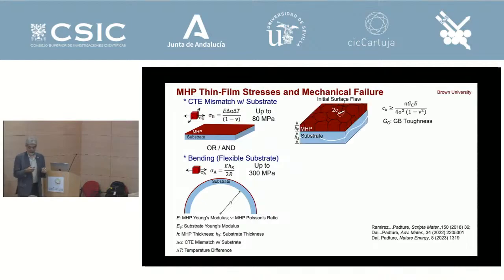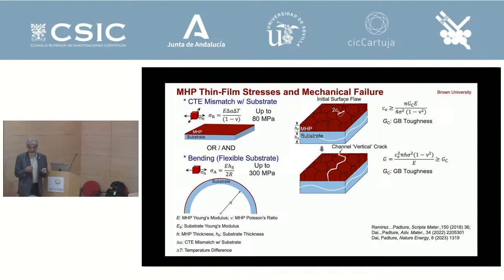But you have these residual stresses, which can be amplified if it's bending. And then you can have cracks, there are always cracks, and these stresses act on those cracks. When the cracks reach critical size, they will propagate, and you get what are called channeling cracks through the thickness of the film. These cracks by themselves are actually not a problem because they're very thin, and so the area reduction is maybe 1%, because the carriers, the electrons and holes, are going up and down, so they don't care where this crack is, right? A loss of only 1% area is nothing.